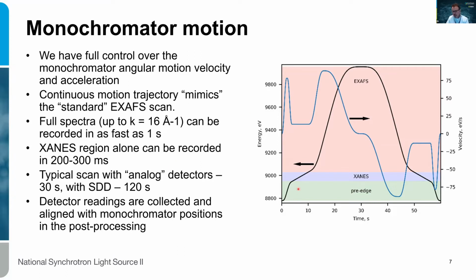So we can go, for good samples, down to 1 second for a full EXAFS scan, and a few hundred milliseconds for just a XANES region. So the typical scan is in the 30 seconds range.